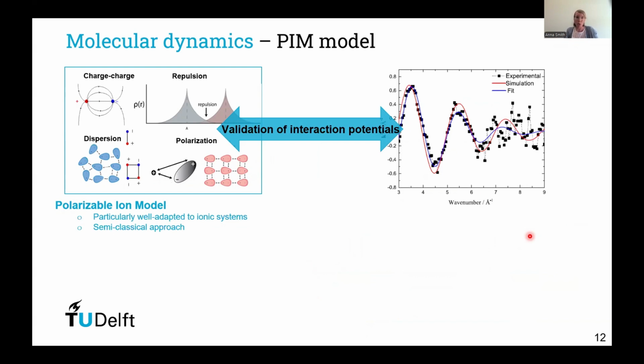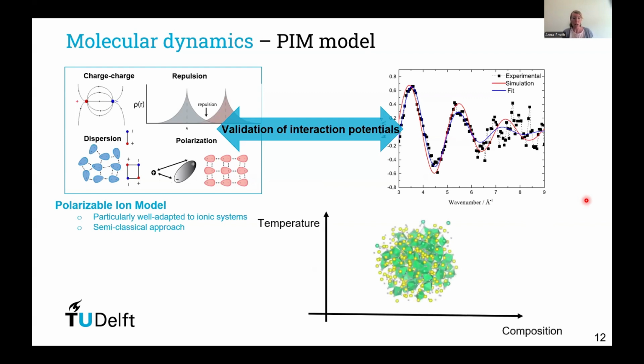We do that using a so-called polarizable ion model that is really well adapted to ionic systems. And with these MD potentials, which we have, we can simulate EXAFS data and compare to our experiments. This allows us to validate the interaction potentials of the molecular dynamic simulations. And in case there is a discrepancy, we can also fine-tune the interaction potentials to get a better agreement with the experimental data. With that, we have validated interaction potentials from molecular dynamic simulations, and we can then use the MD to get a detailed information and insight on the structure at any temperature and composition in the salt system, including in regions that we have not measured experimentally.